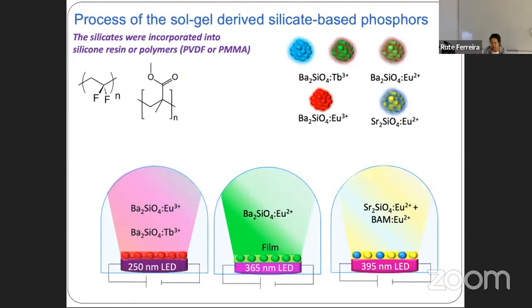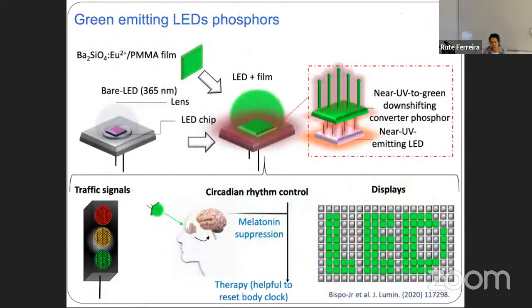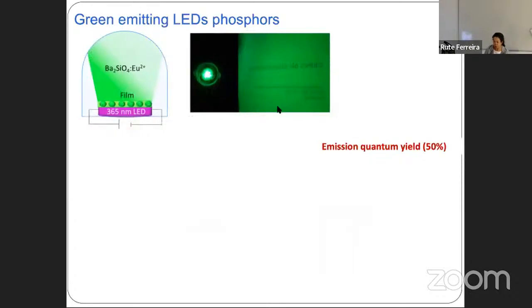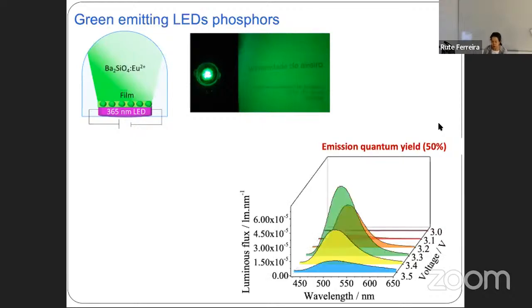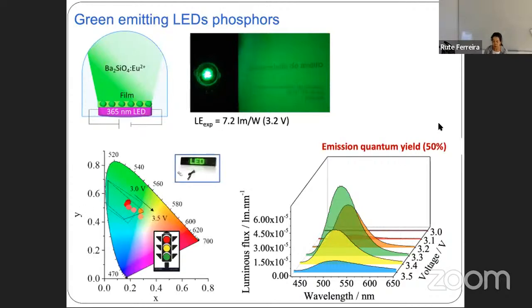And today I selected two examples to show to you. One is the case of a barium silicate that was incorporated into a PMMA film, polymethyl methacrylate film, that was used to coat a bare UV chip emitting at 365 nanometers. This photo illustrates a prototype and the bright resulting green light arising from the high quantum yield of the phosphor, that is around 50%. The prototype emission was studied as a function of the ultraviolet chip operating conditions, revealing a minor color variation in the green. The luminous efficacy, in this case around 7.2 lumens per watt, is one of the best values in the literature for this kind of materials.